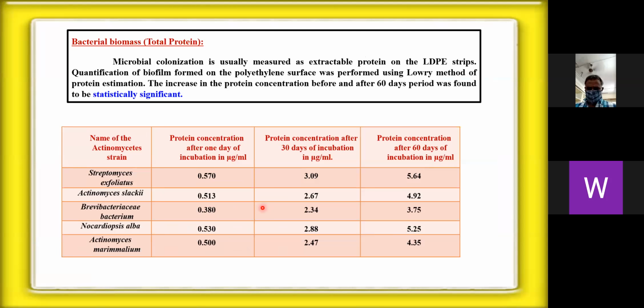The bacterial biomass, total protein. The microbial colonization is usually measured as extractable protein on LDPE strips. Quantification of the biofilm formed on the polyethylene surface was performed using the Lowry method, and thereby Streptomyces exfoliatus was found to contain a maximum protein concentration of 5.64 μg per ml, followed by Nocardiopsis alba with 5.25 μg and Actinomyces slackii with 4.92 μg, followed by the other two strains, Brevibacteriaceae and Actinomyces mammalium.